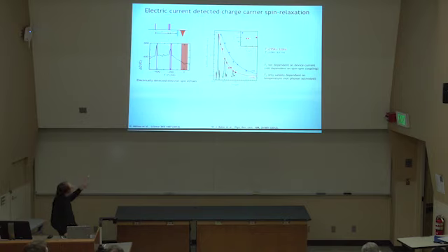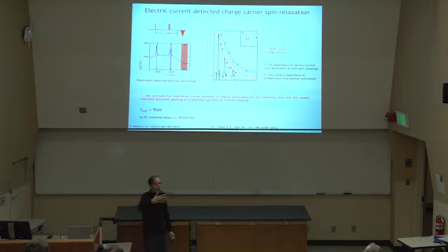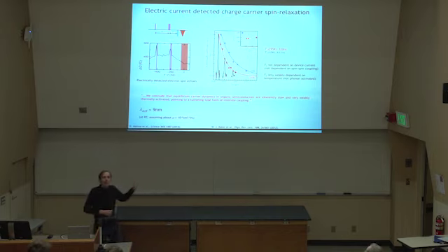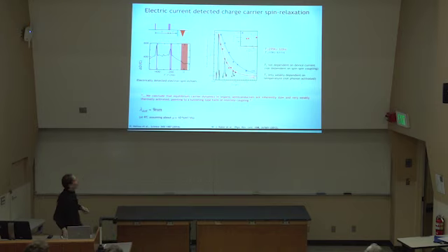From this, then, you can also measure T1 times. And from all this, combining it with mobilities that you find in these systems, you can get, for instance, spin diffusion lengths. And that brings us back to what I mentioned earlier. Yes, you gain in coherence times and spin relaxation times. Both T1 and T2 are longer in these systems generally. Remarkably, because of hyperfine fields, they're all basically within the same order of magnitude, but you lose with mobilities. And again, that's a different topic to bring this together. But at least we have the experiment to scrutinize these observables, which is what we need in order to optimize spin diffusion in these materials.